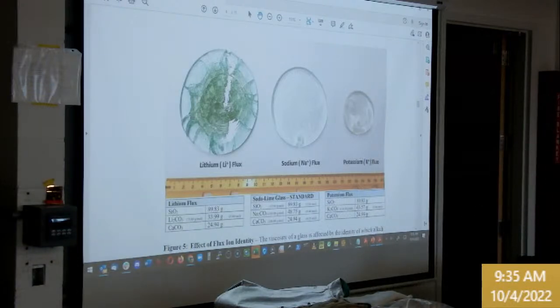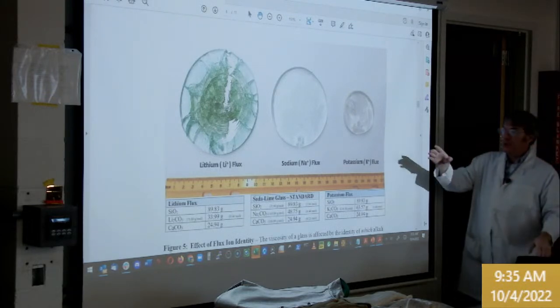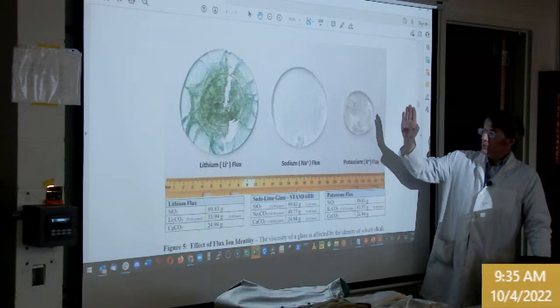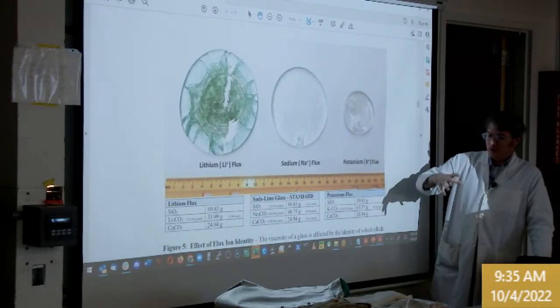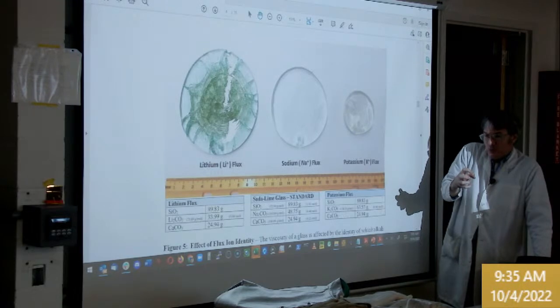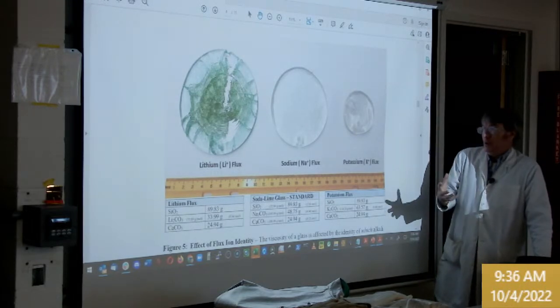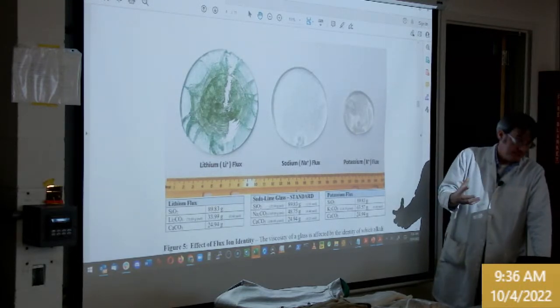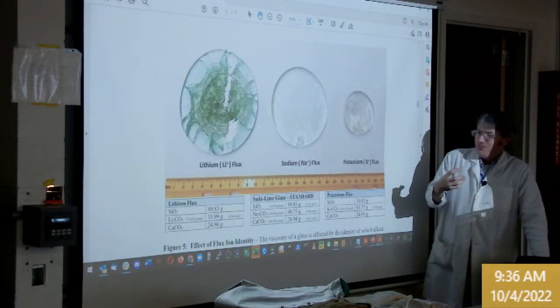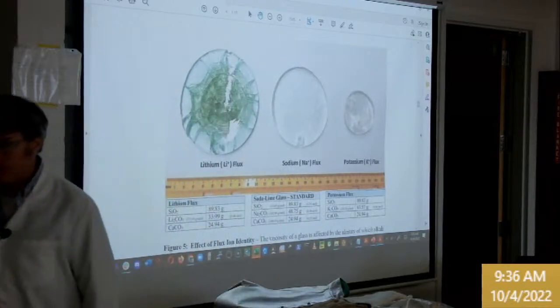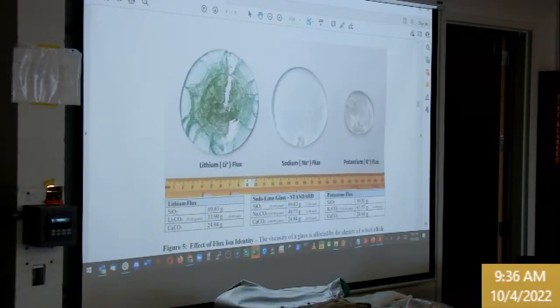Potassium, on the other hand, is such a tight flux at our pour temperature. I really should be pouring these at like 1400, but when you pour potassium at 1200, it has so much tension left when it cools, they almost always explode. Okay? So now by explode, here's what it looks like. And there probably will be a few that do today. So it's not like a grenade that goes off like this. You know, that's not what to expect.